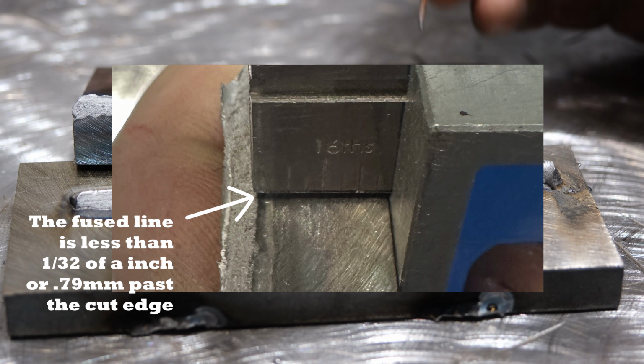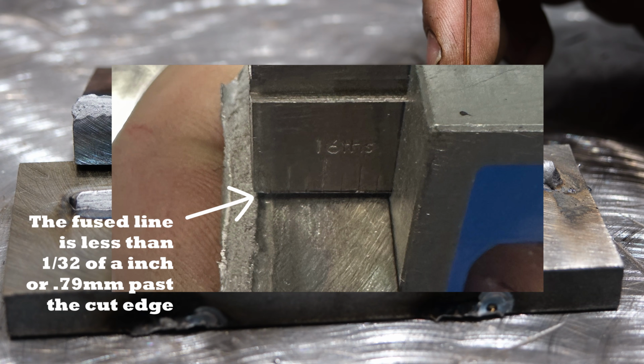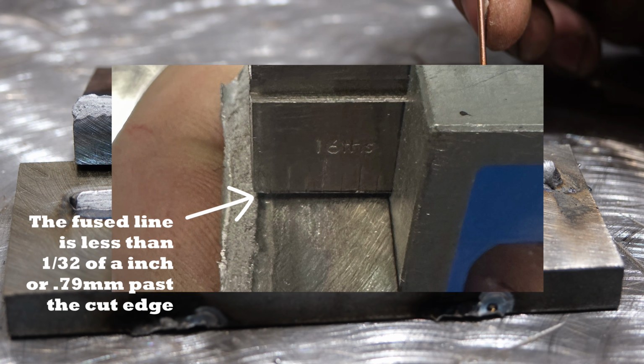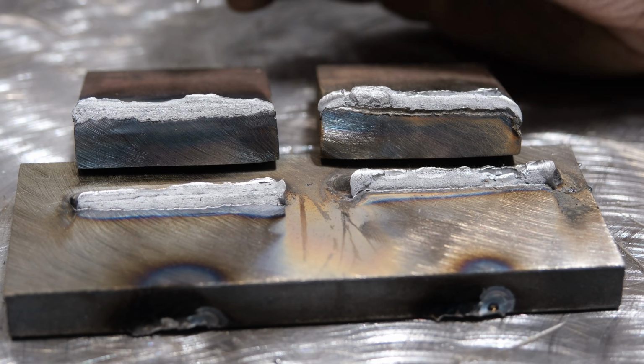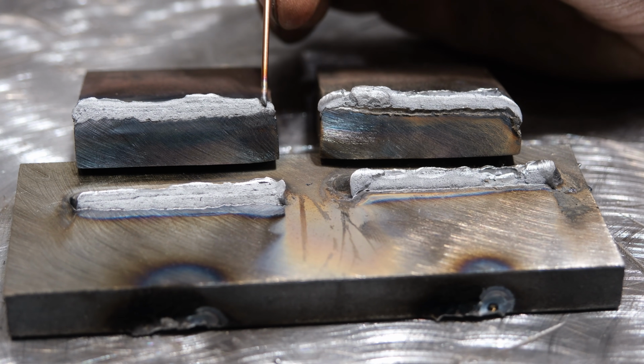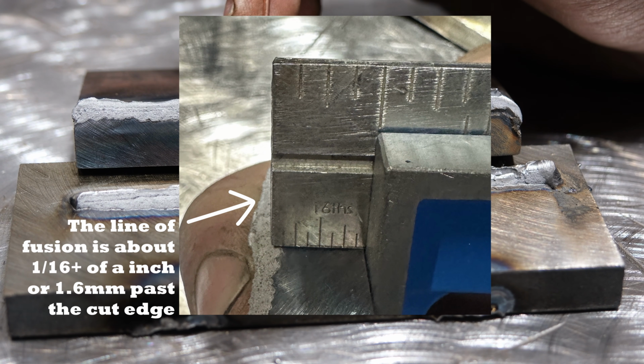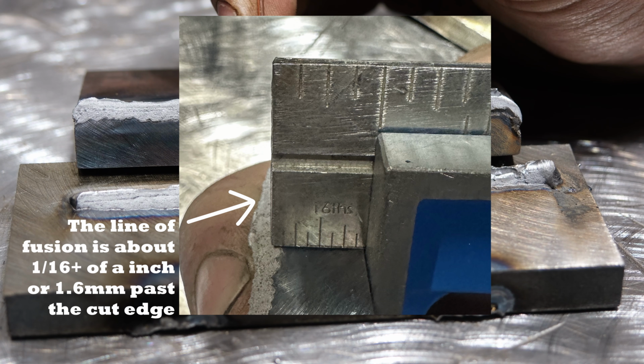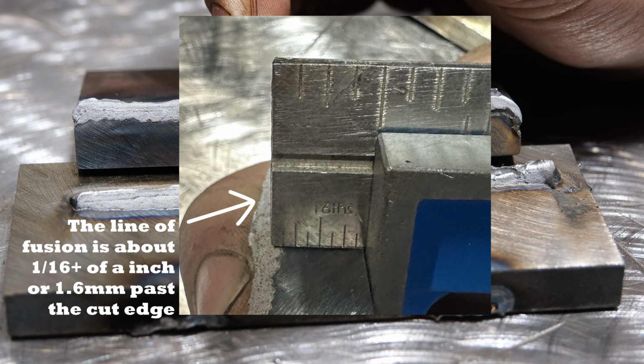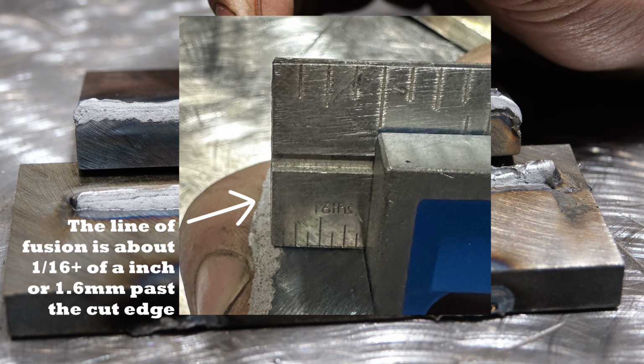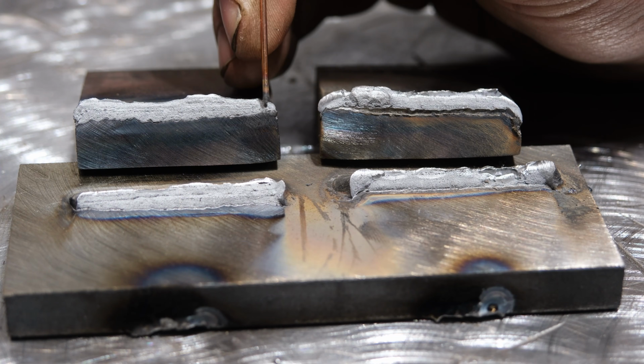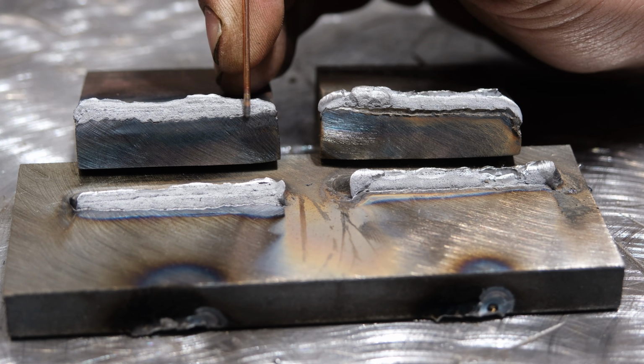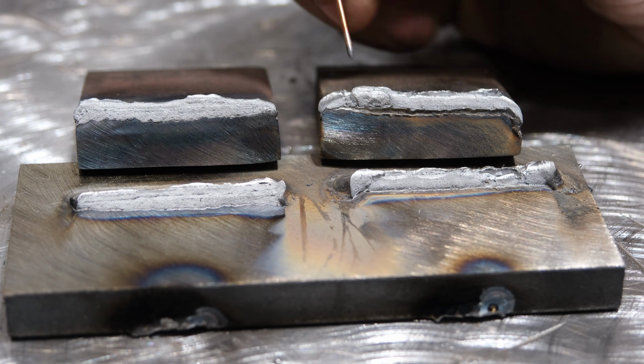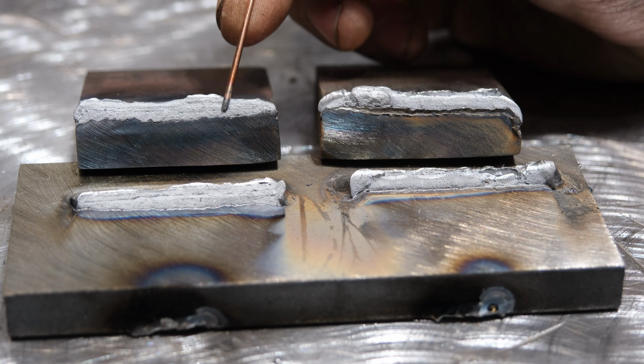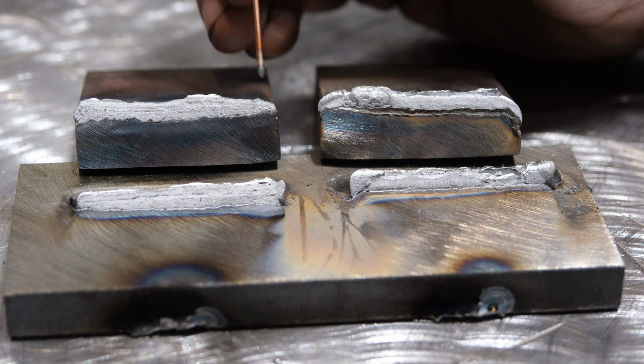So this is what you're going to see on a typical short 2-inch weld with 7018. This is very typical. Now, when you look at the TIG weld, things are a lot different. Now, keep in mind, I started here and moved over to here. There is no evidence of a lack of fusion other than at the very, very start, it is not penetrated in as much. It's still past the edge of the upright plate, but you can see how it curves down as the molten pool got hot and everything's good. But we do not see any evidence of this on this TIG weld, nor would you typically ever see that.